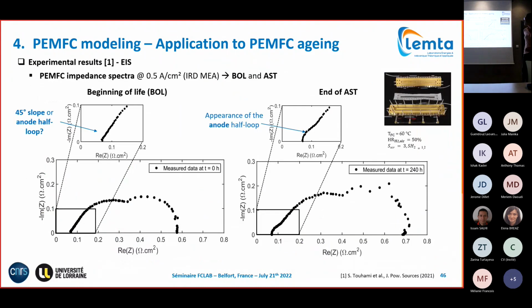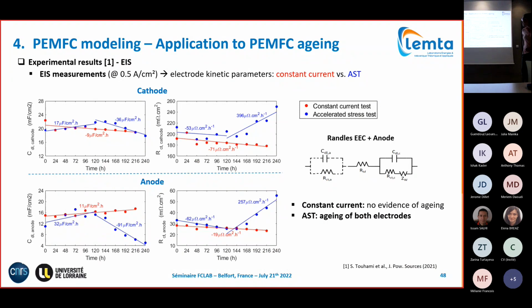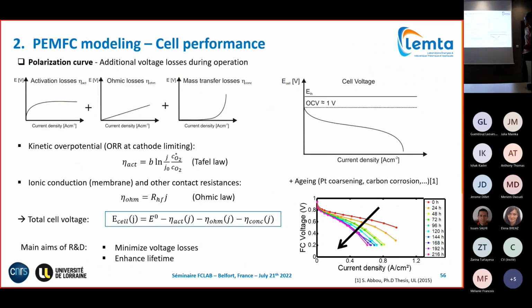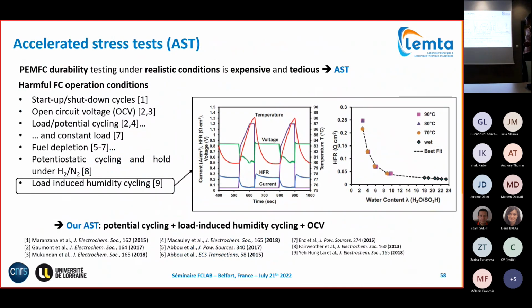There was also my question, maybe something similar to what you already asked. Are you sure, did you validate the AST itself? Are you sure that with that profile you are really reducing the degradation that we can face during operation? Actually, the literature gives different references for different kinds of AST that exist. For example, open circuit voltage, primarily linear, low potential cycling, is primarily corrosion. Actually, it's not the operation high current, low current, high potential, low current, low potential that will induce corrosion. These are transient. Sometimes even the level of high and the level of low makes the total difference. Exactly. And this is the key point.